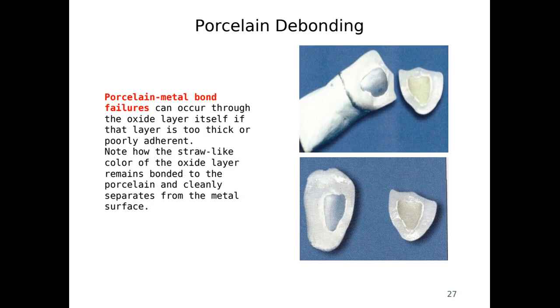So what's going on sometimes? Why does the porcelain break from the alloy? Well, sometimes the porcelain is not bonding well with the alloy because the oxide layer itself is either too thick or the procedure wasn't done correctly. Note how the straw-like color on the oxide layer remains bonded to the porcelain and clearly separates from the metal surface. So the oxide layer is transferred to the porcelain instead of being on the coping. That's the reason why the porcelain didn't bond with the metal.